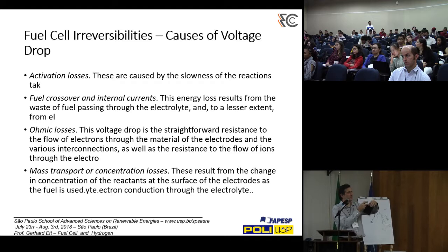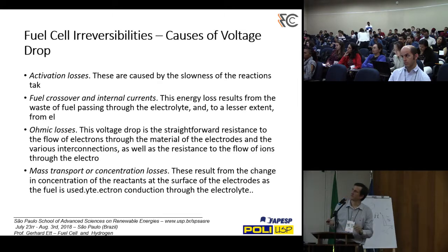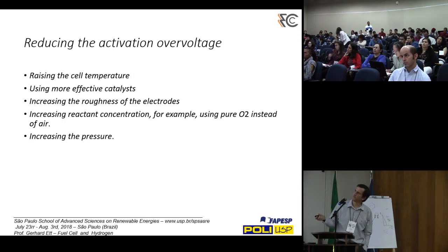Crossover happens when the hydrogen goes directly to the cathode and reacts with the oxygen without producing energy. When you start a PEM fuel cell, at the beginning you don't have water in the membrane. Then it can happen that the hydrogen crosses the membrane and goes directly to your cathode. If you don't control it, the membrane will burn. Then you need to control the humidity at the beginning of the cell. Also, you have ohmic losses, and also mass and concentration loss, a diffusion problem.